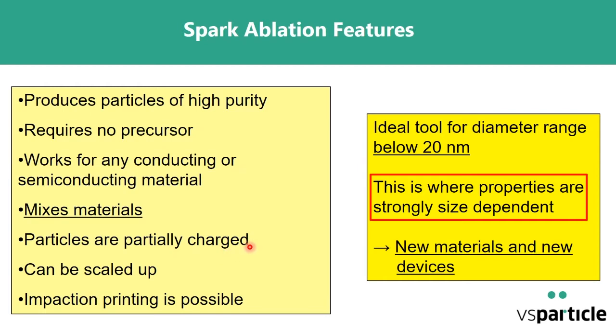That's also a very useful thing, because if they are charged, first of all, you can use an electric field to bring them to any point you want. You can apply an electrostatic force to them, and that can be very useful for building up devices out of these particles. And it can also be used to select a particle size. And in aerosols, that's very simple. You use a differential mobility analyzer when the particles are charged, and you can pick out one size. The method can be scaled up because obviously you can use 100 or 1,000 sparks instead of one spark. And impaction printing, I will also come back to that, is possible.